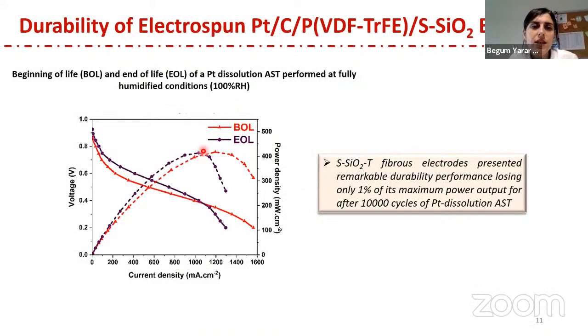These electrodes also show excellent, remarkable durability after the platinum dissolution accelerated stress test. The power density loss at maximum power output is around 1%.